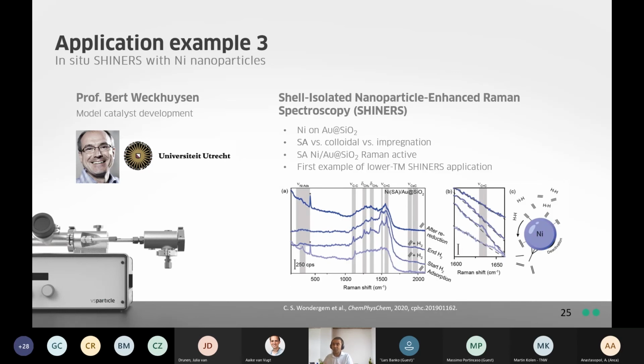The third application that we have also comes from the group of Professor Bert Weckhuysen. This is an in situ SHINERS study. SHINERS is an advanced Raman spectroscopy based technique in which they can use gold nanoparticles encapsulated by silica to enhance the Raman signal of a reaction that's taking place on the surface of a model catalyst. So in this case, they studied nickel-based catalysts. They compared the preparation of these SHINERS active materials using spark ablation, which is our technique, a colloidal approach, and an impregnation approach, the latter two being more conventional approaches within heterogeneous catalysis.